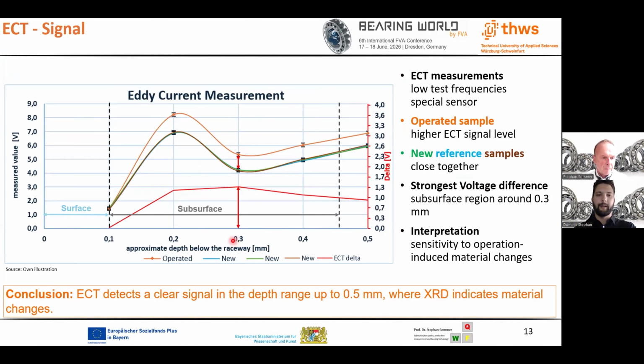This slide shows the eddy current signal measured with low test frequencies in a special sensor setup. The operated samples show a clearly higher eddy current signal level compared with the new reference samples. The new reference samples remain close together, which indicates that the reference condition is reproducible. The strongest difference appears in the subsurface region, around 0.3 millimeters.